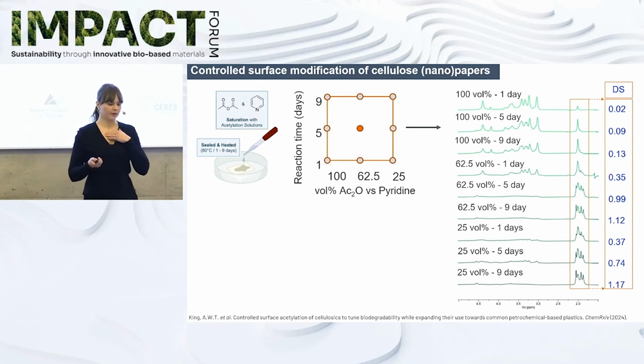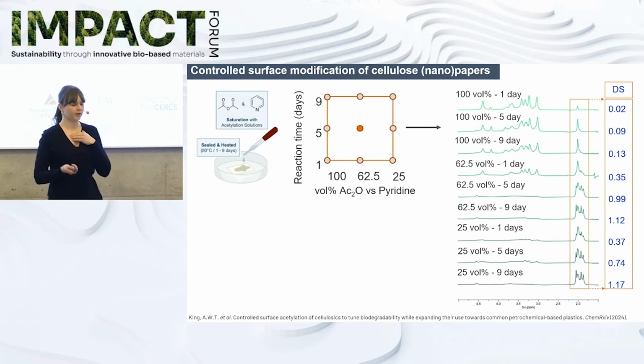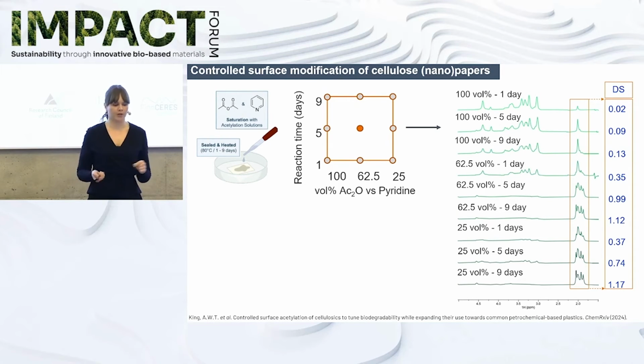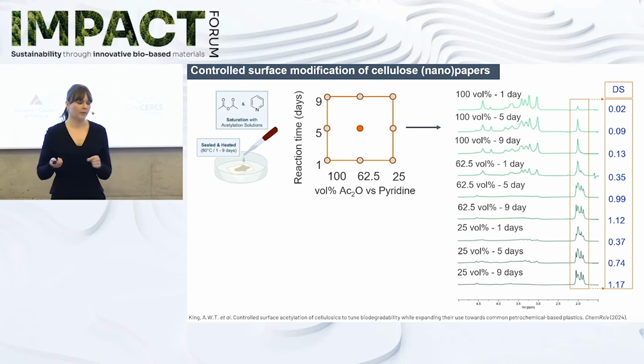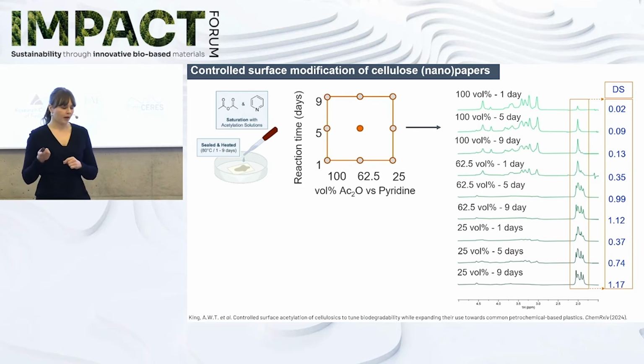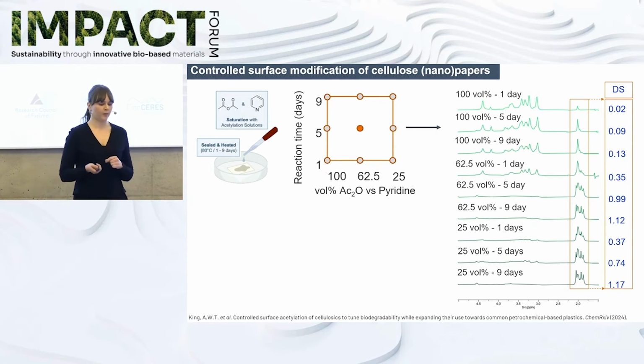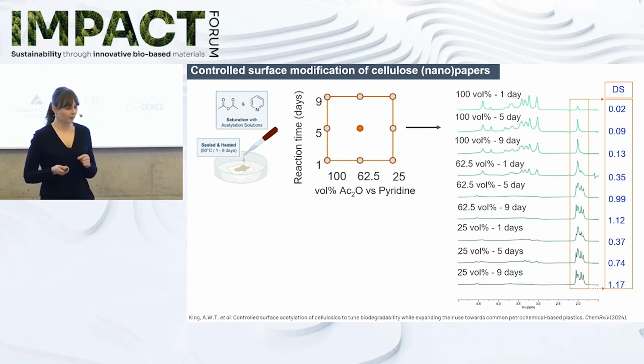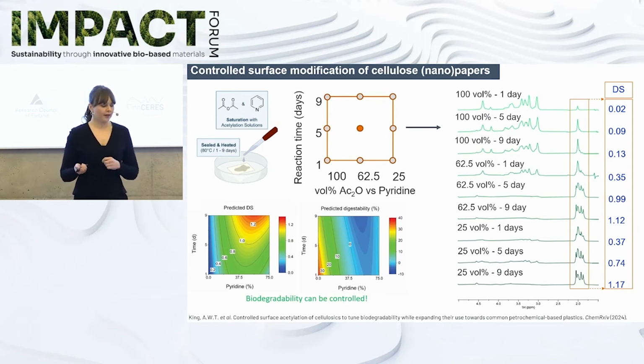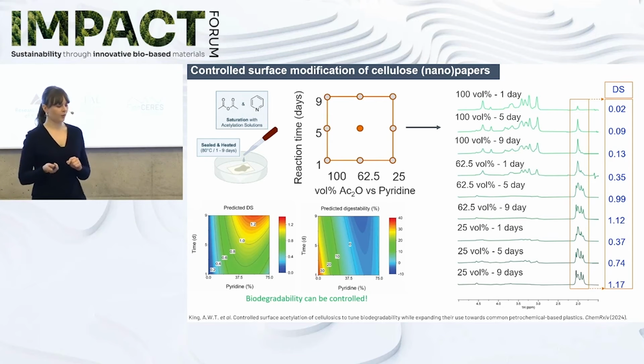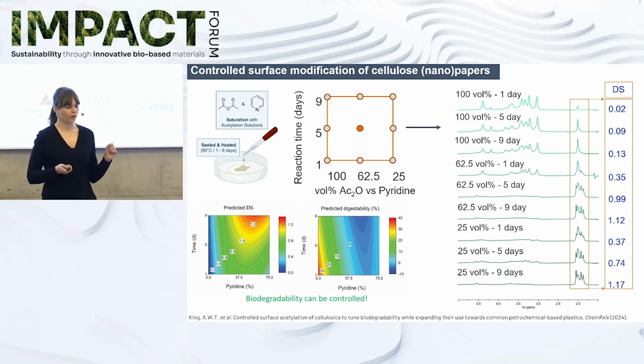So here are the NMR results from all these 9 different test points, so different reaction times and reagent concentrations. And from the peaks, we can calculate the degree of substitution, which is the degree of modification. And we actually see that by controlling the reaction time and the reagent, we can control the degree of modification. And really, with the mildest conditions where we do not have the pyridine, which is the catalyst in the reaction, we are able to reach very low values of degree of modification. And from these experiments, we are able to build up models where we can predict the degree of substitution and the digestibility, meaning the degradation, also outside these reaction points, so we can see where we have the highest or lowest digestibility. So really the biodegradability can also be controlled on the surface.